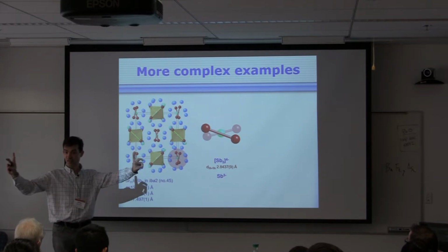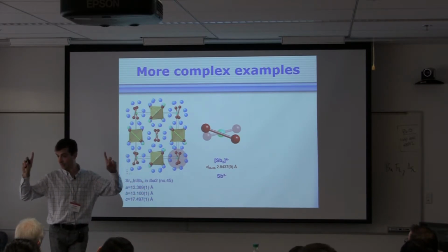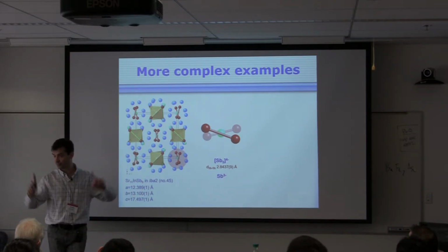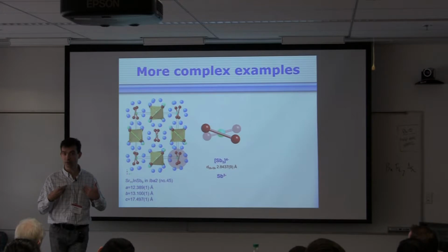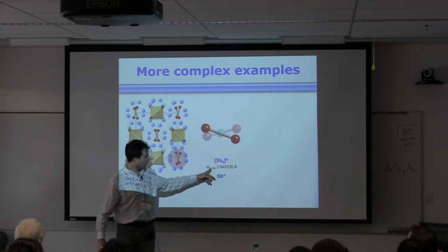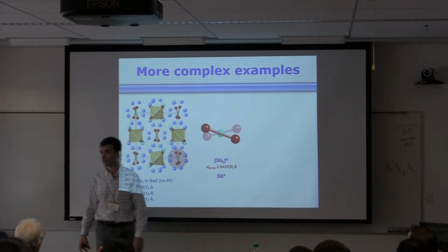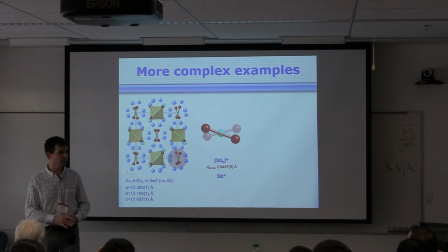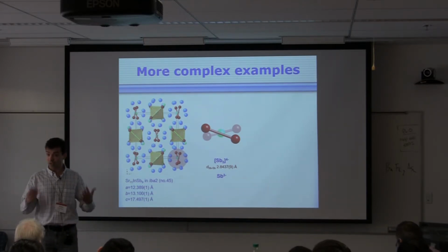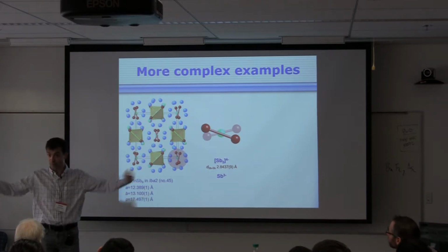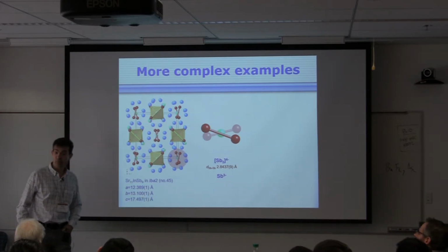The distance in elemental antimony is 3.06 angstroms. And I'm standing in front of you telling you that I reduced antimony and formed antimony-antimony distances of 2.85 angstroms. I would have to shoot myself if I believed this. Reduction means breaking bonds. So what happens here?